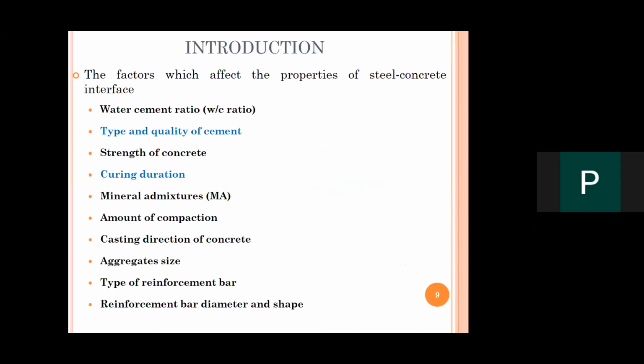No, sir. Fine. So till now, we understood that at the steel-concrete interface, there is a porous zone thickness, and people were assuming that porous zone thickness while predicting the service life. In the present research, we have experimentally tried to find out this porous zone thickness. From our research, we understood that these are the different factors which affect the properties of the steel-concrete interface, or the engineering properties of the steel-concrete interface. What do I mean by engineering property? One is the porous zone thickness. Second is the different kinds of hydration products which are formed at the steel-concrete interface.